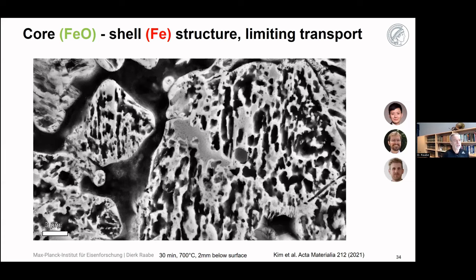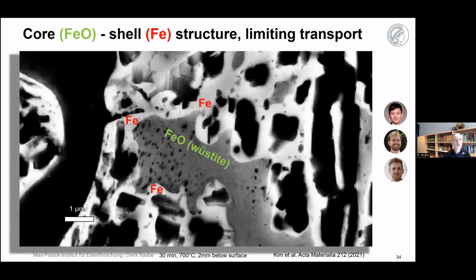When I zoom out again a little bit to a somewhat coarser scale, now we have a bar of one micron again, and leave the atomic scale for the moment. We now cut such a sintered iron oxide pellet open and look at how it looks in a partially reduced state. We are now in a hydrogen reduced oxide after 30 minutes at 700 degrees, and see 2 millimeters below the pellet surface the inner area where the Wüstite is remaining, which needs to be reduced. And you see that very fine outer film of iron around it. That is what you saw before in the microscope movie from the top only.